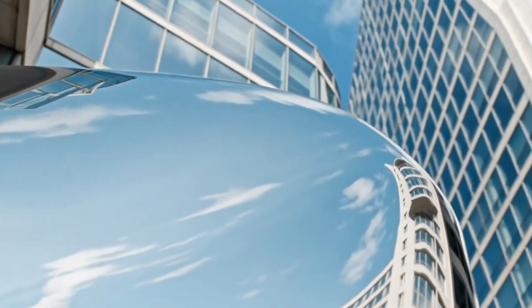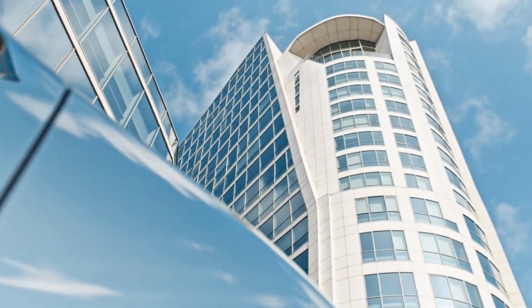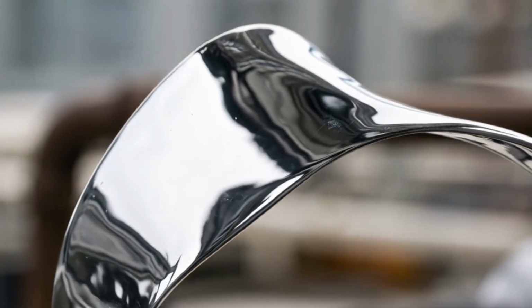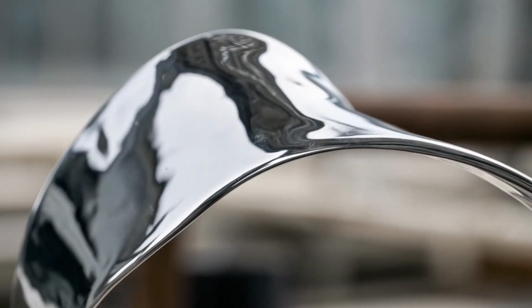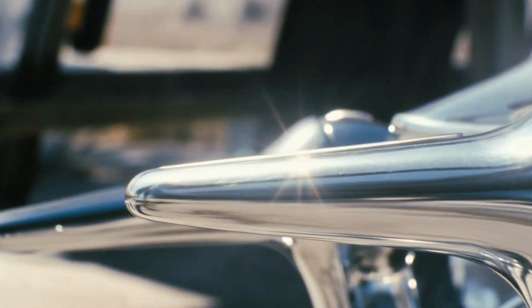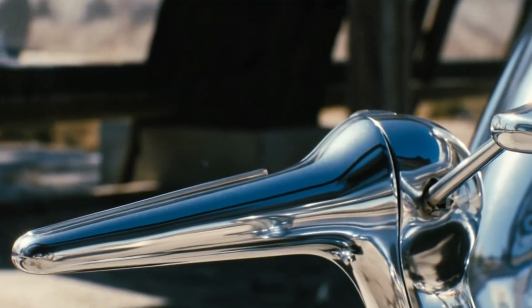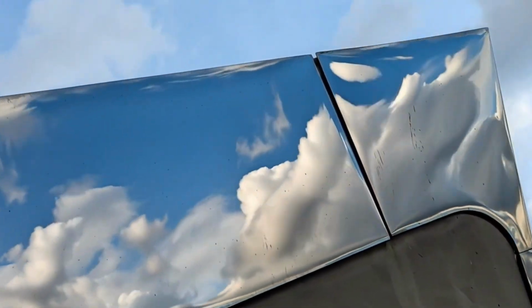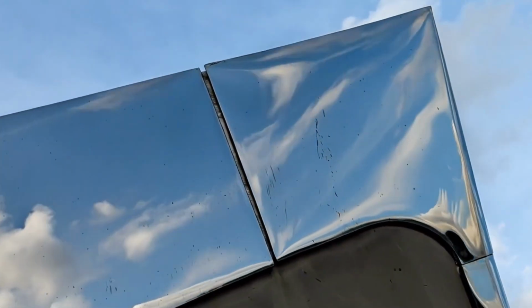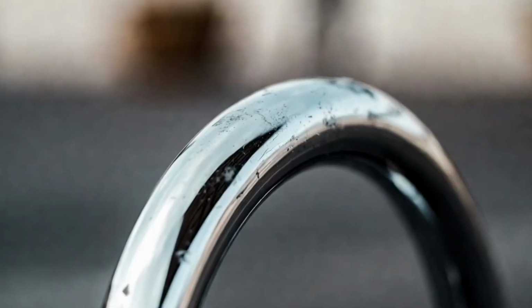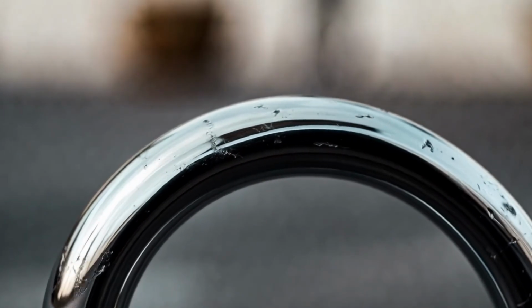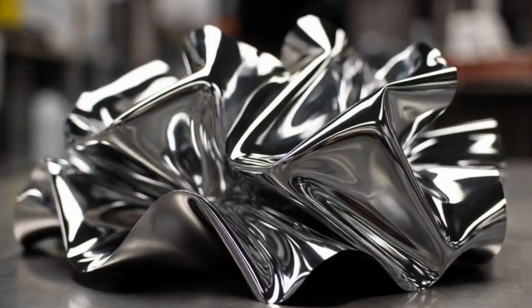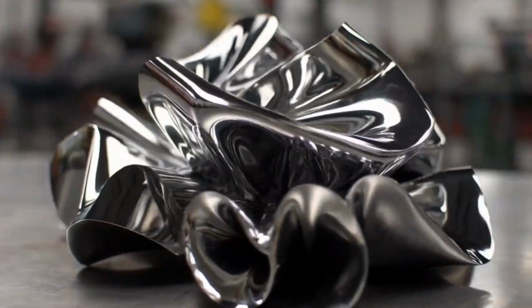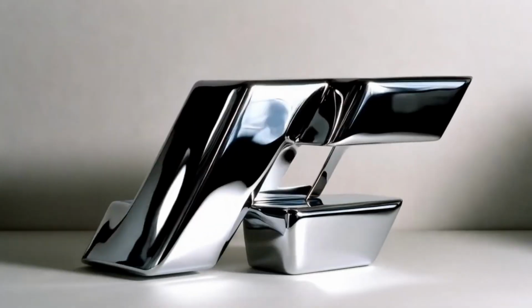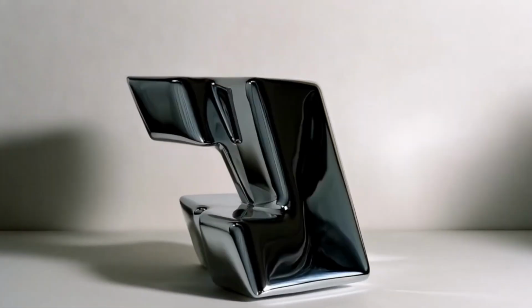The mechanism of this phenomenon was understood later. At chromium content of 10.5% or higher, a very thin film of chromium oxide spontaneously forms on the surface of the steel. Its thickness ranges from 2 to 3 nanometers. This is approximately 30,000 times thinner than a human hair. The film is transparent, so the steel looks like regular steel, not a green-painted surface. It is also self-healing. If scratched in the presence of atmospheric oxygen, it will repair itself within seconds. This is why stainless steel does not rust. Not because it is special in itself, but because chromium constantly builds an invisible protective shield on its surface.